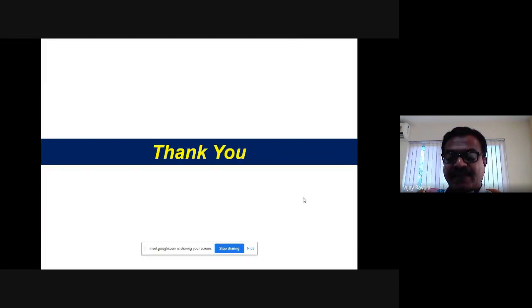The high density is 3.3 milliseconds and the low density is 1 millisecond. We made these, and we could see that they withstand both the top and bottom shock levels and absorb those shocks. These have all been successfully field trial tested at TATA. Right. So these are some of the things advanced processing at ARCI has been doing. Thank you.